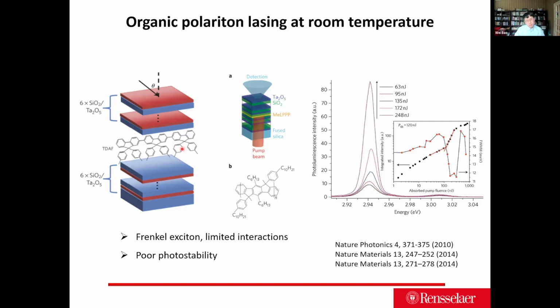But that's also bad because these are Frenkel excitons, which means the excitons don't interact with each other. The emission probably only relies on the one molecule instead of many molecules together in this cavity region. So they have limited interaction strength. For a lot of the Bose-Einstein condensate physics experiments, you need the particles to have certain strengths of interparticle interactions. So those systems are relatively poor in terms of that.